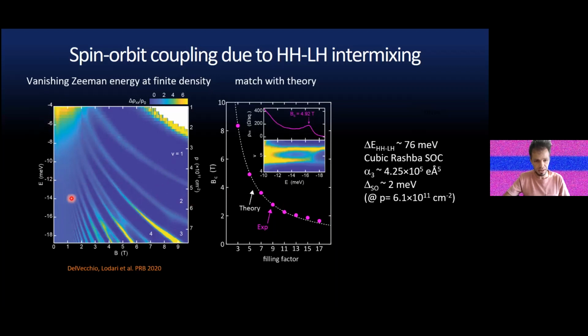If you look at the Landau levels, at some point the spin split bands cross and there is a vanishing Zeeman energy. This happens at a certain point in magnetic field and filling factor, at a critical field, from which you can extract the energy splitting. We've done so in this plot. You see here how experiments and theory match nicely. You can extract a splitting of around 75 millielectron volts, which again means a really large splitting between the bands. From this, we can estimate all the parameters related to spin orbit energy, at least in a 2D system.